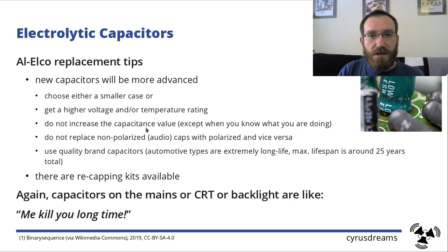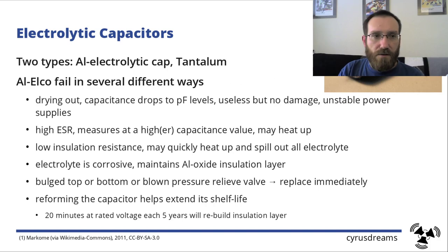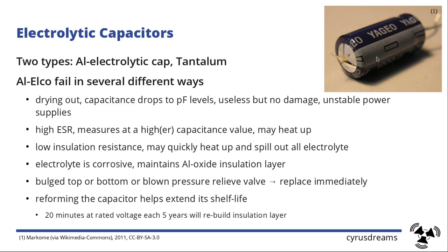You should not increase the capacitance value, even if you can get that in the same size as the old one, except when you exactly know what a circuit does, because some circuits don't cope well with too large capacitances. And do not replace non-polarized capacitors for audio circuits with polarized or vice versa. So if you have to replace capacitors on the headphone jack or line output, make sure that you get the proper type. If the schematic, it's always nice to have the schematic, tells you it is a polarized one or a non-polarized one, use the one that's appropriate for the job. The polarized ones, let's go back one slide maybe, have this marking on the negative side here. That is an indicator, this one is the minus, that this is a polarized capacitor and needs to be replaced with a polarized capacitor.